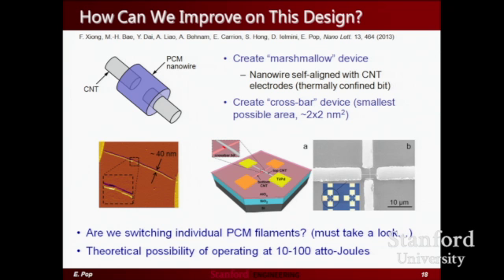So if you can actually confine the heat to a very, very small nanometer-sized volume, you're going to be able to bring down the power consumed significantly, right? So of course, no big surprise. This is what the marshmallow devices look like. This is of course just a cartoon. These were actually about a factor of 10 more energy efficient already than what I showed you on the previous slide. And right now we're making even smaller ones.